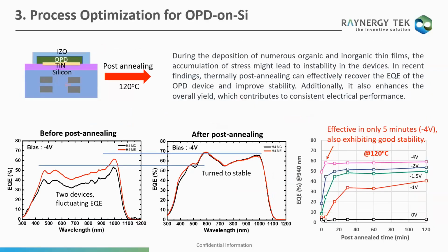And how about the temperature wise? After we finish the device, we actually do a post annealing at 120 degrees Celsius. You can see that before the post annealing, we found that it is actually not quite stable. But after we do the post annealing after the entire stack is built, it turns stable, with QE registering 40% on the silicon, which goes back to normal, and it can sustain for more than 120 minutes. So we believe that the material has good thermal stability over time.